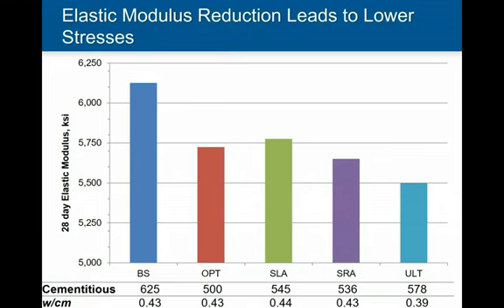Well, for a bridge deck, let's say, one of the things we're seeing across the board in minimization of cementitious content and employing shrinkage mitigation, we're seeing characteristic drops in elastic modulus. And if any of you are structural engineers in the audience, this may sound like a bad thing. When the elastic modulus drops, that generally means in structures that our deflections are going to be higher. But when we're talking about something like a newly constructed bridge deck, we want our elastic modulus to be lower, because what that tells me is the stresses due to restrained shrinkage are diminished. So this is a good thing.